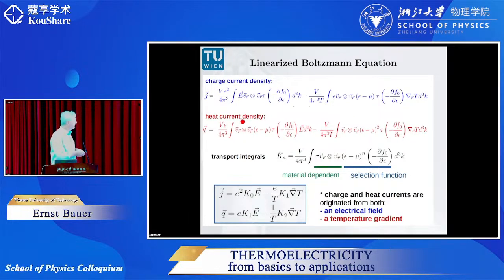Of similar importance is the heat current density, where also the velocity plays a role, but differently to a simple assumption in the charge carrier density, the energy, of course, plays a significant role as well. Since we do have metals, the energy is just of importance if there is some distance to the Fermi energy. Because we remember a particle can be scattered only or can move only if there are free states. And free states in a metal are just in the proximity of the Fermi energy.